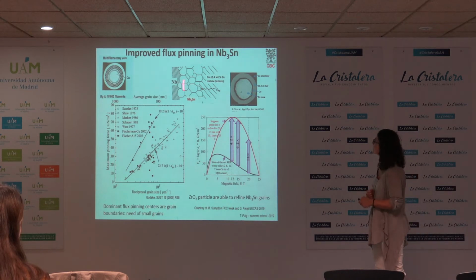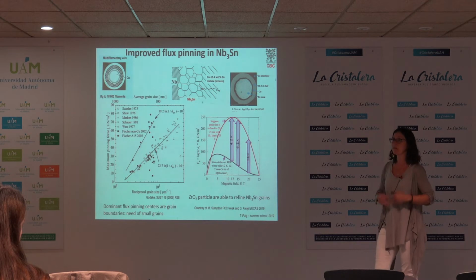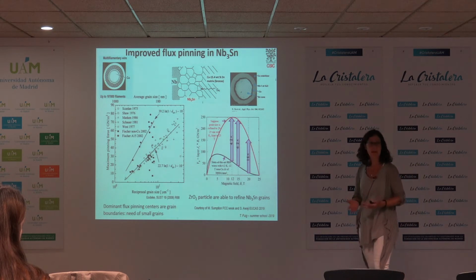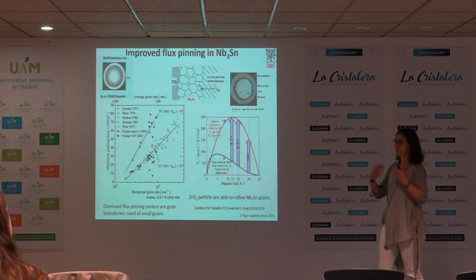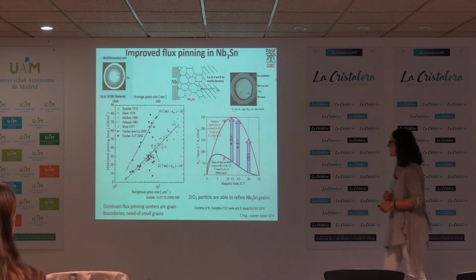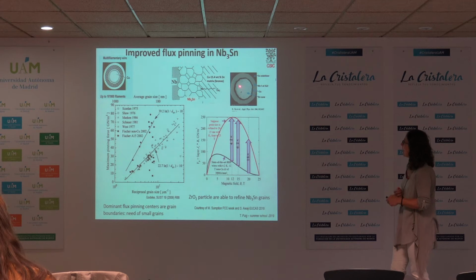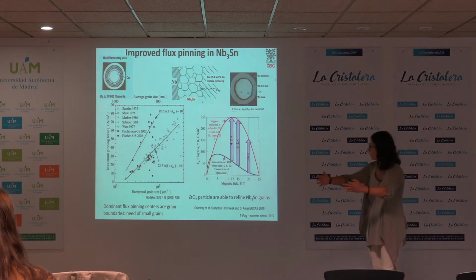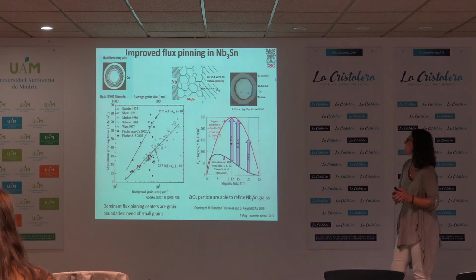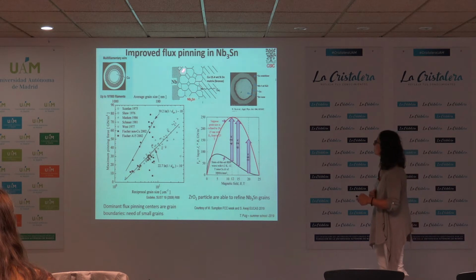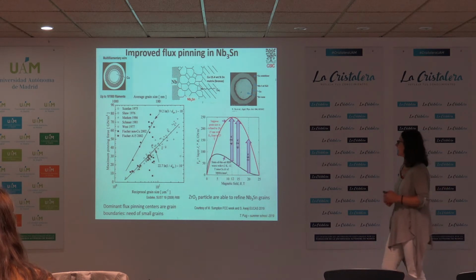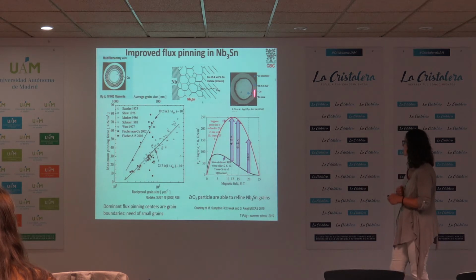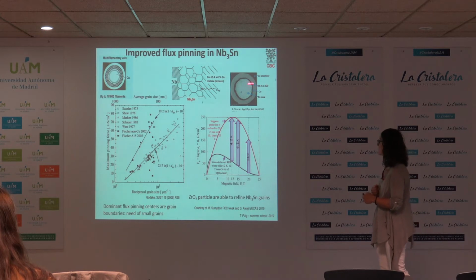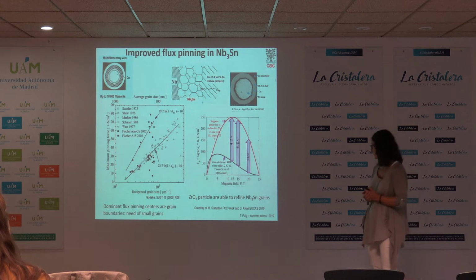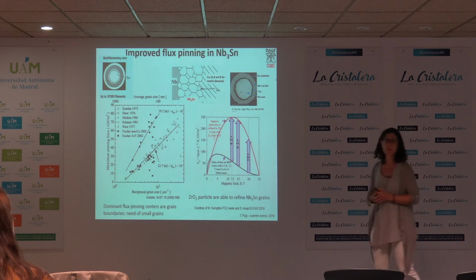In fact, it has been shown that the grain size of the niobium-tin being generated is what at the end determines how much current we can pass, because the grain boundaries are the pinning centers in this material. So there is now a lot of effort to get more tin into the niobium-tin, for a higher density of the material, but also narrower grains, so that we have many more grain boundaries and therefore increase the pinning force. It has been seen, for example, that by just adding 1% atomic percent of zirconia into the niobium, they are able to more than double the pinning force of this material.